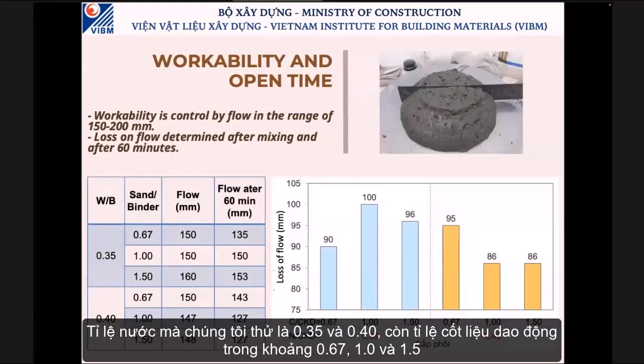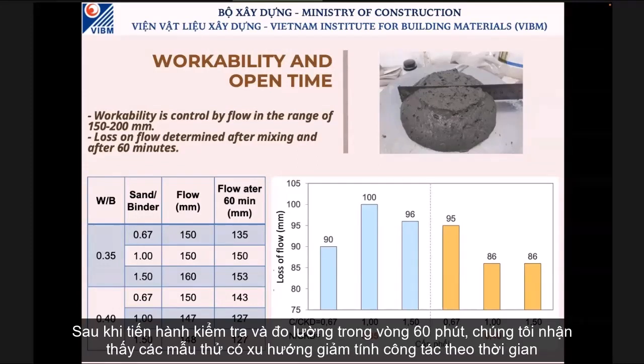The workability, we test with different mix water binder ratios: 0.20, 0.35, and 0.40. Sand binder ratio varies at 0.67, 1 and 1.5. And we test the workability and we measure after 60 minutes, and we found that a number of different mixes decrease the workability after time.